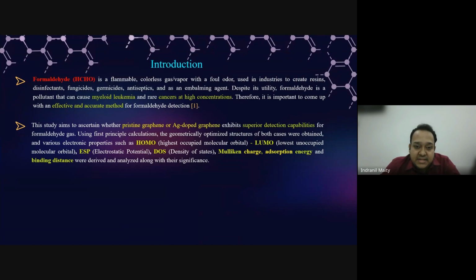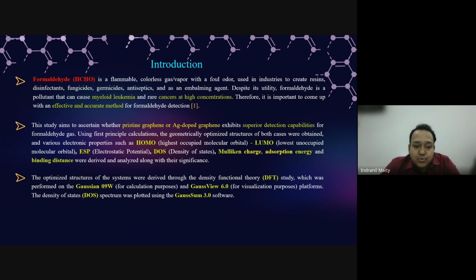One is pristine graphene and the second one is silver doped graphene. And the results are basically based on DFT-based computations, having HOMO, highest occupied molecular orbital, LUMO, lowest unoccupied molecular orbital, ESP, electrostatic potential, density of states, Mulliken charge, adsorption energy, and finding the binding distance. So the software tools which have been used: basically Gaussian 09W for the calculation purpose, GaussView 6.0 for the visualization purpose, and the density of states spectrum was plotted using GaussSum 3.0 software.